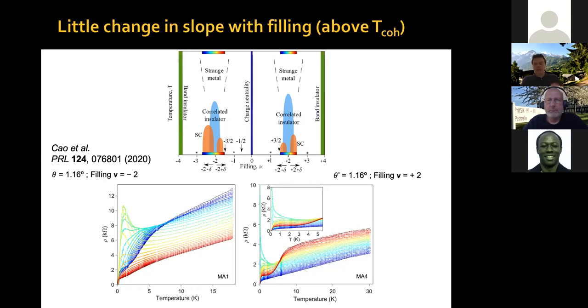It is much more natural to have this type of anisotropic response and nematicity if you have a non-S-wave order parameter, in particular P-wave or D-wave or combinations of P-wave and D-wave, okay? And we do not know which ones. You can read a little bit there about which ones might perhaps be most likely. Some of these have been suggested by people, D plus iD and different types of D and P-wave superconductivity. But we don't have experimental evidence of the symmetry of the order parameter at this moment.